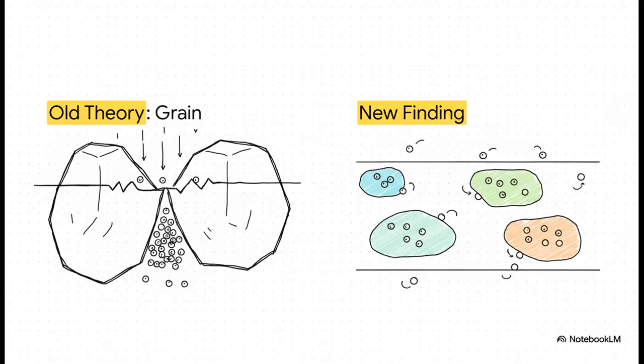And here's the really cool conceptual leap. The old theory was static, right? It imagined atoms just kind of passively settling at the edges. But what they found was a totally dynamic process. The heat wasn't just a gentle nudge, it was giving the atoms on the surface of that growing film enough energy to actively zip around and self-organize. It's a process called surface diffusion. They weren't just settling, they were actively sorting themselves into these perfect cobalt-rich and chromium-rich zones.